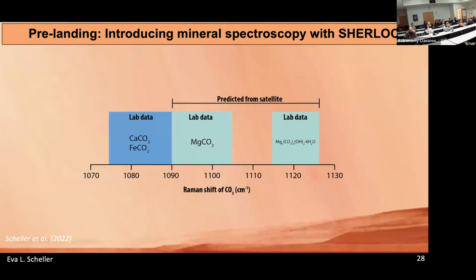It was predicted from satellite that we would observe magnesium carbonates, and so they would have a pretty high Raman shift, either in anhydrous form or in hydrated form. And conversely, if you have a more calcium or iron-rich carbonate, they would shift the Raman shift down. And that's actually something that we can constrain with the SHERLOC instrument.